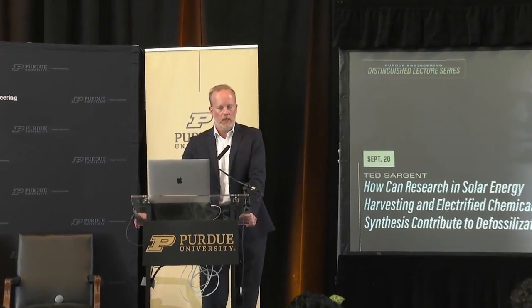Yeah, it's a great question. The answer actually depends on which of the layers in the tandem we're thinking of. So the tandem, of course, consists of a high band gap and a low band gap material. The high band gap materials today have been mostly made by mixing halides, so combining a bromide and an iodide. But those have been introducing the challenges of phase resegregation into a bromine-rich phase and an iodide-rich phase. And so if you're in the computational business, if you can help us crack this problem of either finding a high band gap absorber that doesn't rely on the mixed halides, or a mixed halide absorber that remains stable over extended operating periods at higher temperatures, that would be very impactful for the field.